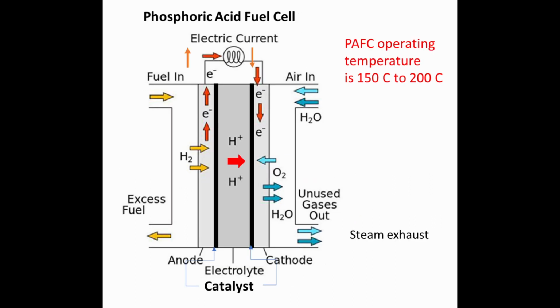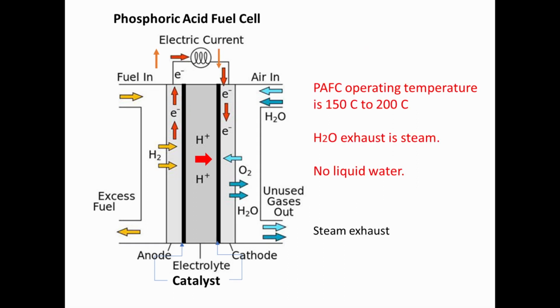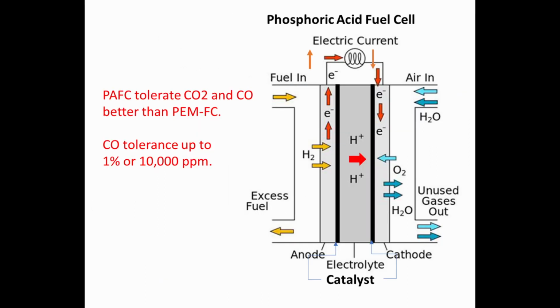The PAFC operating range is 150 to 200 degrees Celsius. This operating temperature allows the water to be produced completely as steam. There are no problems with liquid water in PAFCs as there might be in lower temperature PEM fuel cells. PAFCs have a higher tolerance for carbon dioxide and carbon monoxide than PEM fuel cells. PAFCs can tolerate carbon monoxide levels up to 1%, or 10,000 parts of CO per million parts H2 in fuel, without accelerated catalyst damage or performance degradation.